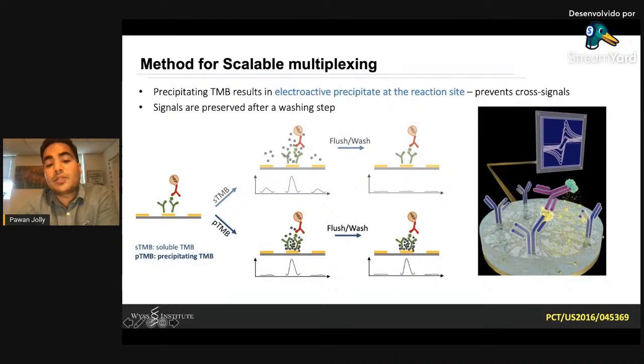So what essentially happens over here is that you have local precipitation of the reaction or of the signal at the molecular binding event. So in this case, it will be in the middle electrode. And because it's local precipitation, you don't pick up the signal from the neighboring electrodes. And this will only happen if you have a reliable surface chemistry, which is specific. And when you flush these electrodes, you can still retain the signal because it has now precipitated on the surface. And that is what essentially helps us to actually detect over the period of 1 week or more.